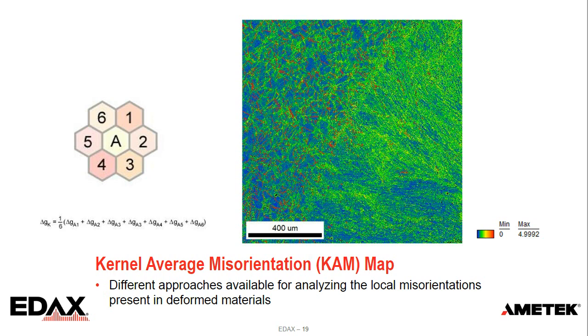Typically for regular EBSD, our precision is somewhere around a tenth of a degree. So when misorientations are higher than that, we can start looking at how those are distributed. We do this in one form of a map called a kernel average misorientation map, or a KAM map, where for every pixel in the map, we look at the misorientation between its six adjacent neighbors, and we take the average of that and color it accordingly.